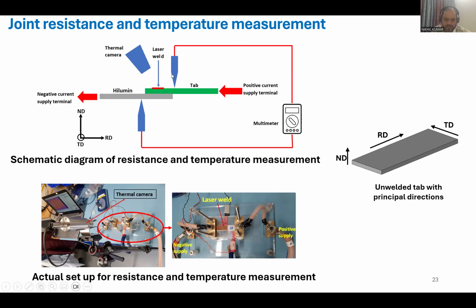We have made some arrangement of probes. One probe is connected close to the weld on this tab, and the other probe is connected to the bottom face of the bottom sheet. Those probes are very close to the weld, so that we can capture the voltage drop across the weld only. Suppose we are passing the current as X amps and the voltage drop is V volts. So the resistance would be V divided by X, because we are capturing the voltage across the weld. That resistance would be the weld resistance because you are not capturing resistance from end to end.